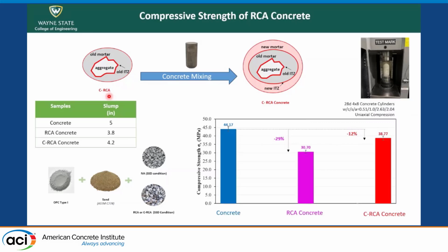What we saw is that our concrete with the recycled concrete aggregate has a 30% lower compressive strength when we compare it to regular concrete. But that was reduced to about 12% lower compressive strength when the recycled concrete aggregates were carbonated. So we're not there yet to have a concrete with recycled concrete aggregates that has a compressive strength similar to that with natural aggregates, but we could use this as non-structural concrete.